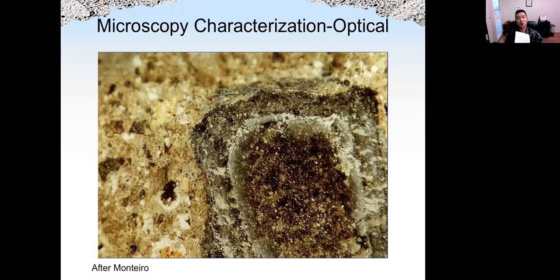So this is the microscope. From the optical microscope, we can see the gel around the aggregate. The gel is generated between silica in the aggregate and alkali from cement. So often we see the gel surround the aggregate. Okay, sometimes the aggregate will also crack. So does the cement paste.